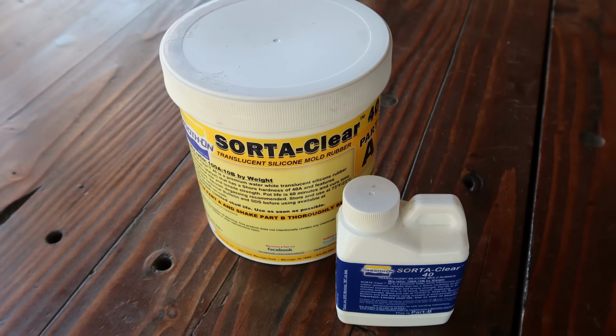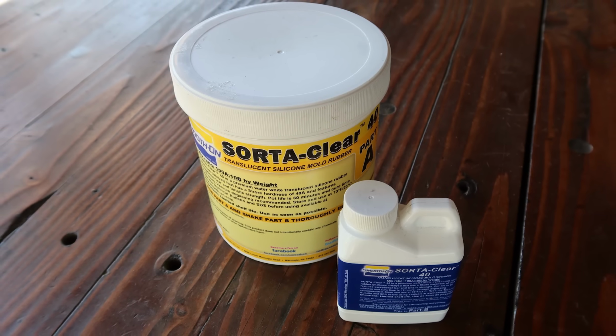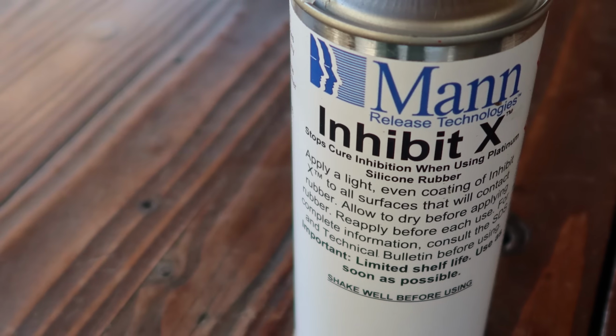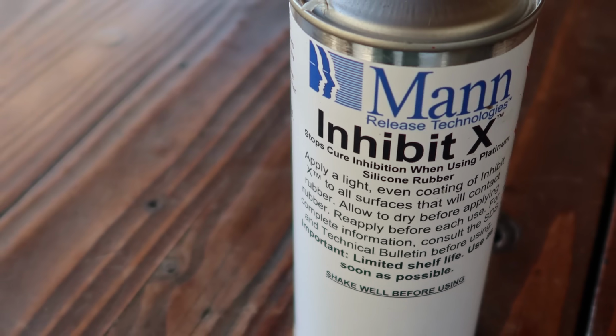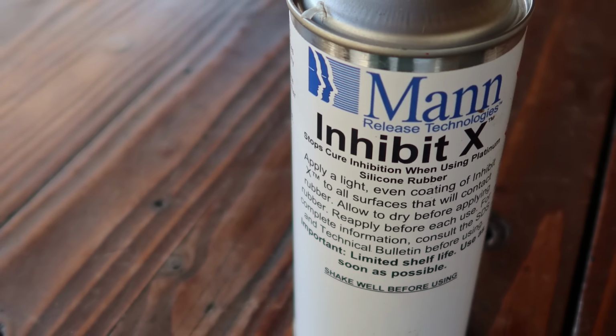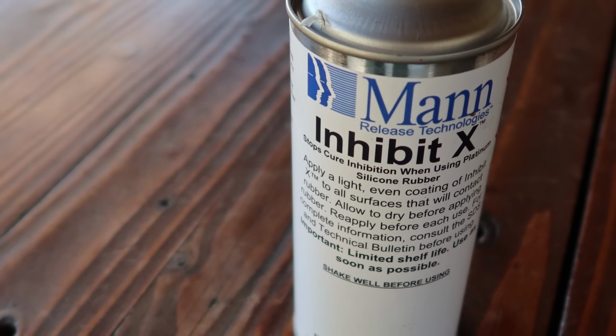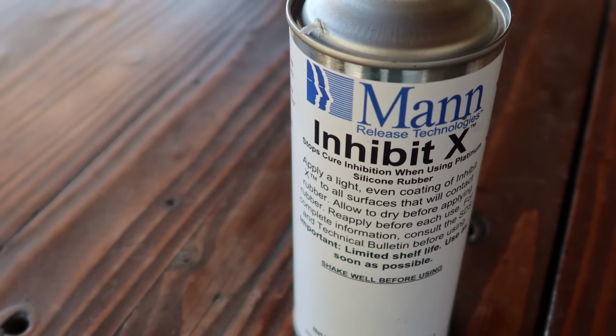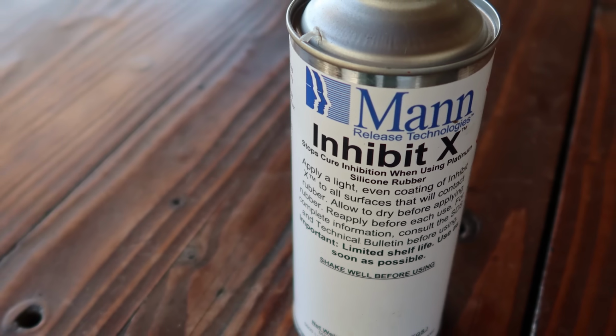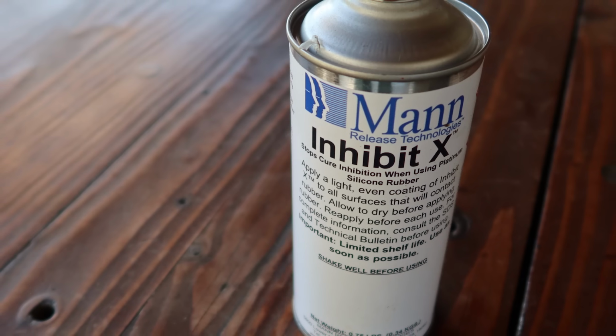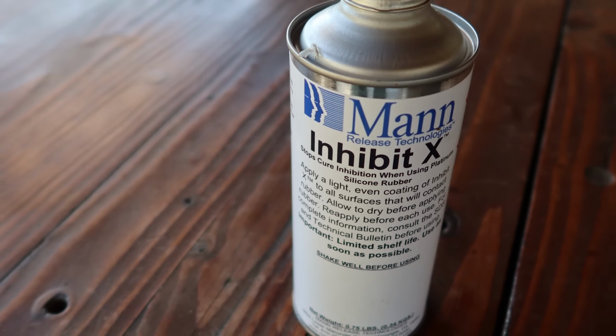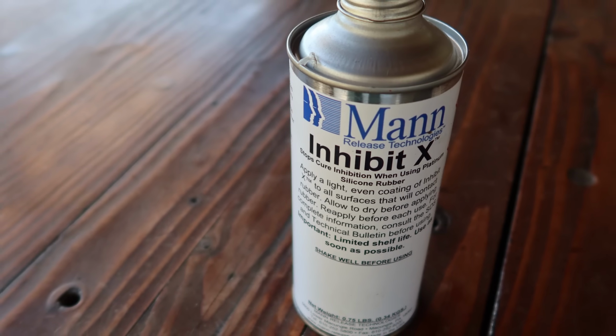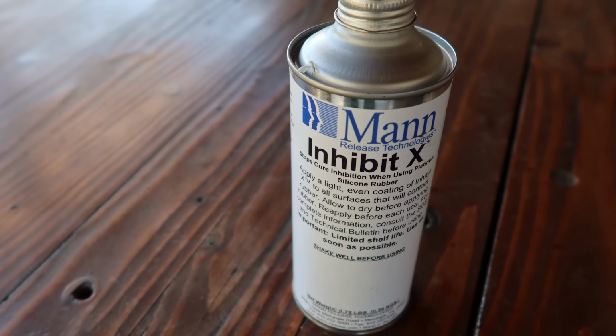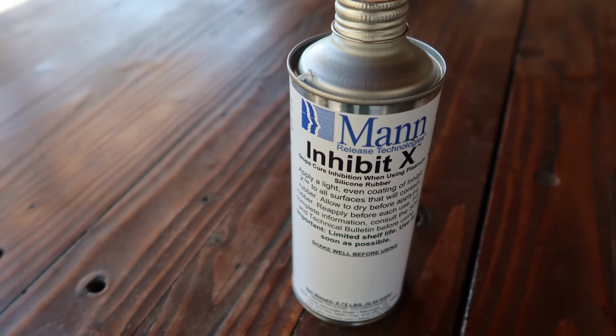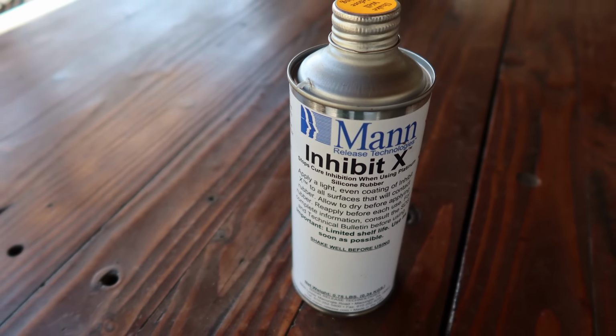The biggest problem I'm going to run into when using a platinum-based silicone is going to be cure inhibition. Generally speaking, platinum-based silicones really don't like being cast into 3D printed SLA molds. Cure inhibition is where parts come out of the mold still feeling tacky and goopy even after they've been given plenty of time to cure. To prevent this, I'm going to be using Inhibit X, which is a solution that you can soak your molds in. It basically creates a barrier around your 3D printed molds to prevent cure inhibition and make sure you get a good part coming out.